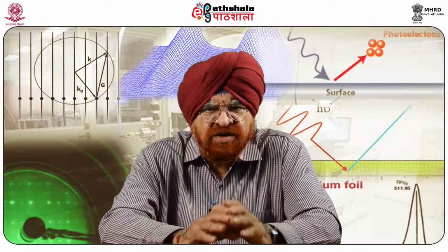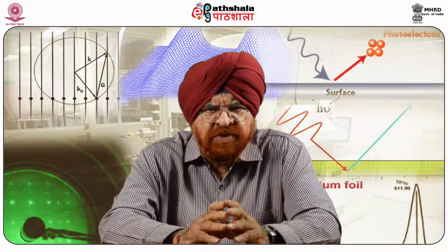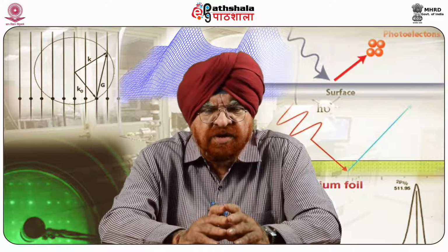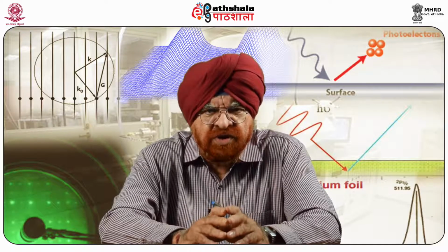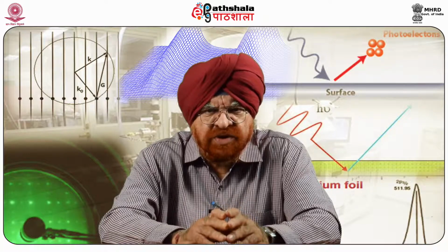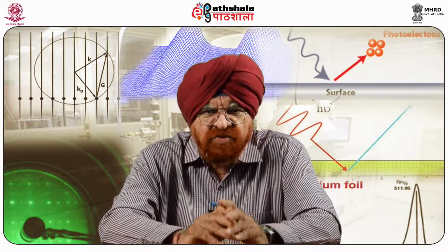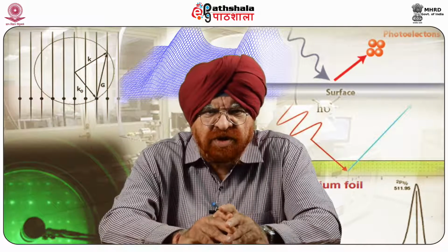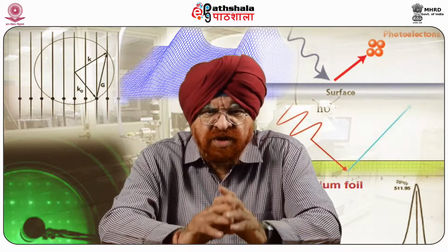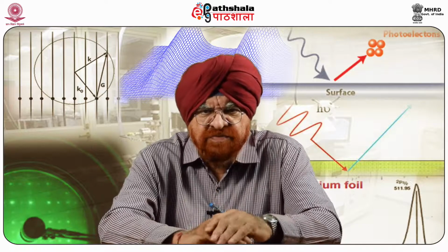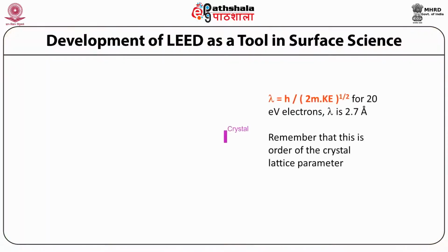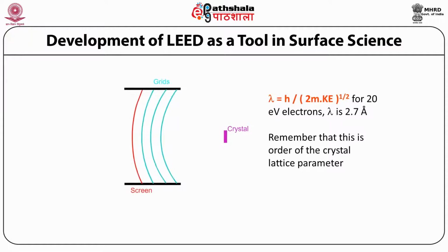RHEED is the standard equipment in the epitaxial growth chamber, providing a great opportunity to monitor surface properties during the growth process. This real-time in situ method makes it possible to control the growth with atomic layer precision. The schematic diagram of this is shown, wherein we take a crystal and the radiation that passes from there,